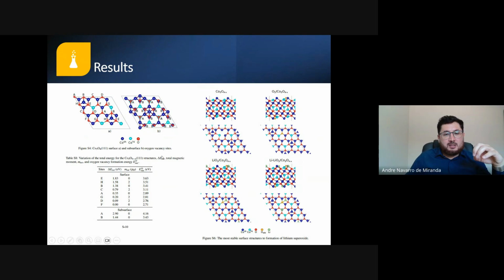Pedro has seen like, okay, if you have like oxygen vacancies, where can it be formed? So you have seen different possibilities here, and the most stable way to form these oxygen vacancies is here in the F place of this structure. So we have here the surface with this vacancy here, and then we have simulated the adsorption of an oxygen molecule here. So it enters in this oxygen vacancy perfect as expected.